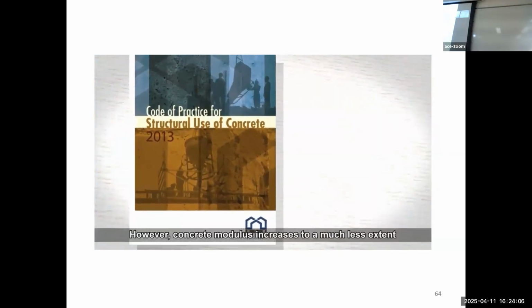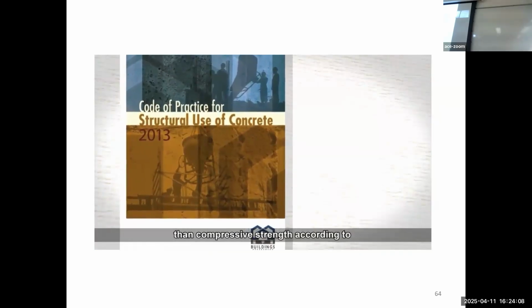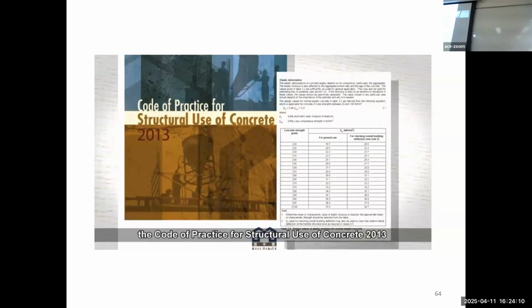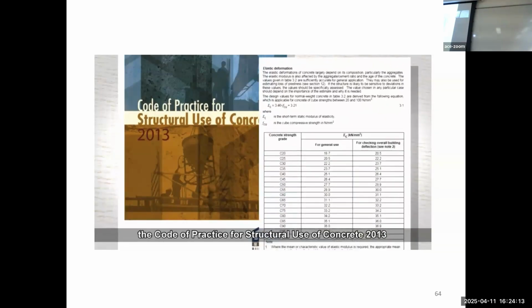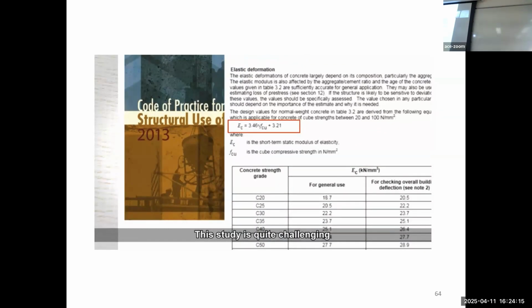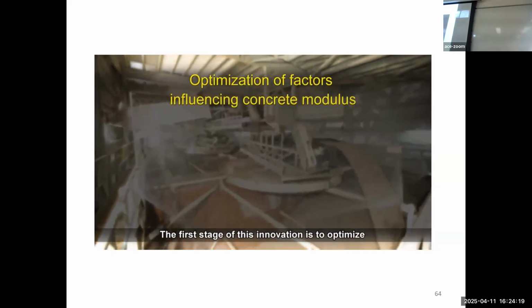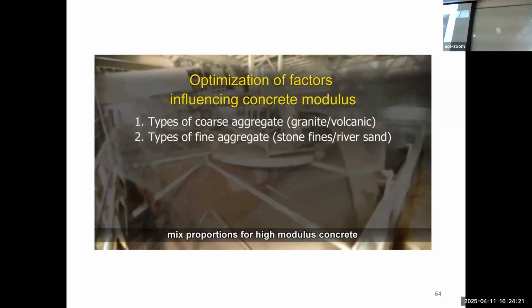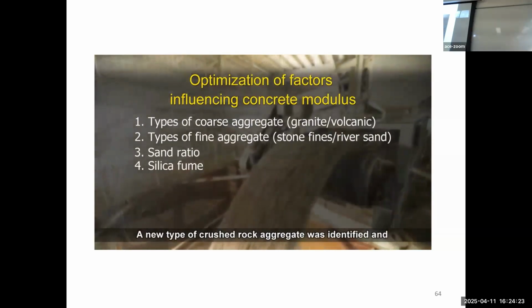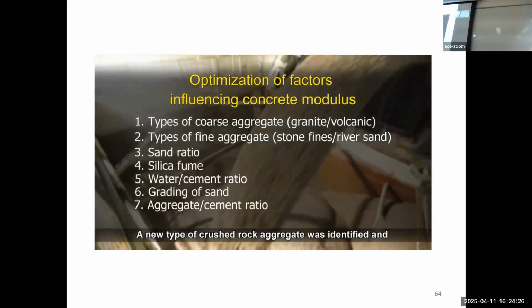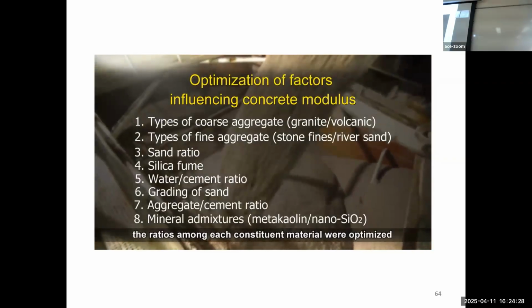However, concrete modulus increases to a much less extent than compressive strength according to the Code of Practice for Structural Use of Concrete 2013. This study is quite challenging. The first stage of this innovation is to optimize mix proportions for high modulus concrete. A new type of crushed rock aggregate was identified, and the ratios among each constituent material were optimized.